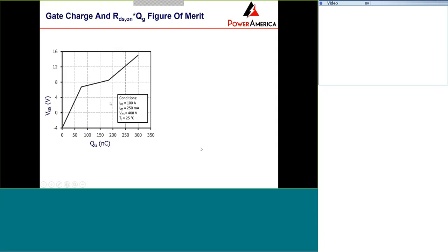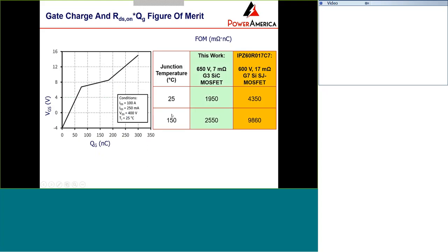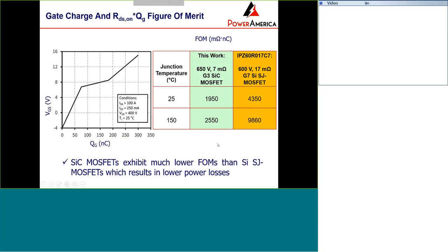And also the charge parameter has been measured and compared, with the figure of merit of the product of the on-resistance and gate charge. As shown in the right figure, you can see that at room temperature the silicon carbide MOSFET devices are better than the silicon superjunction devices, and this number is getting even better at 150 degrees C. So this result has shown that silicon carbide MOSFET at 650 volts exhibits a much lower figure of merit of RDS(on) times QG than silicon superjunction. I will show later actually the price. If you calculate the price of silicon carbide compared to the silicon, the price is not that far off, based on the study we have.